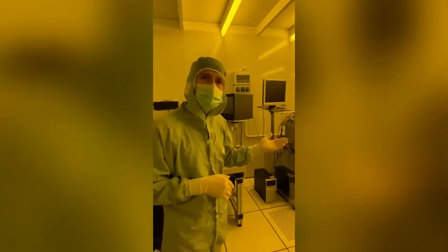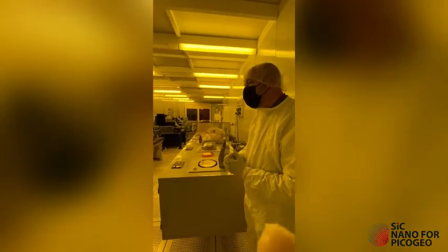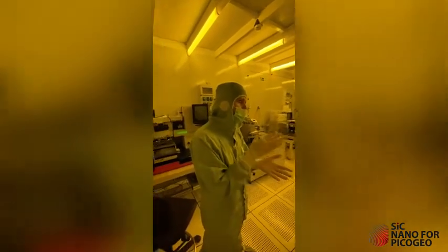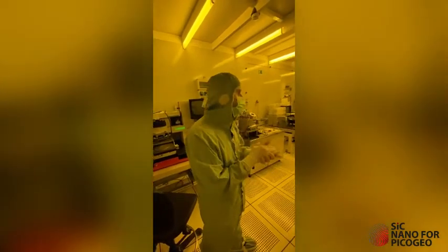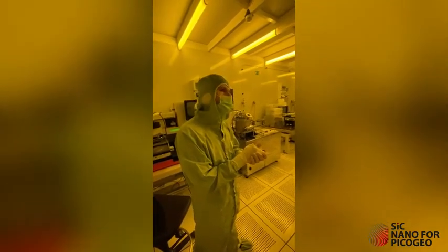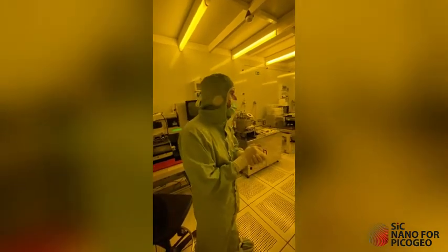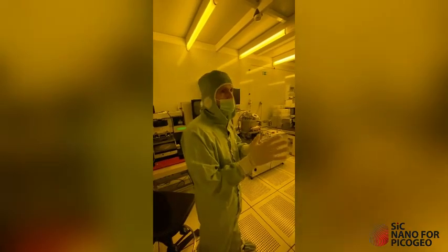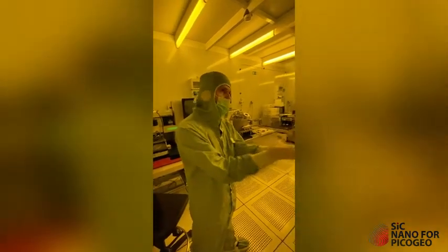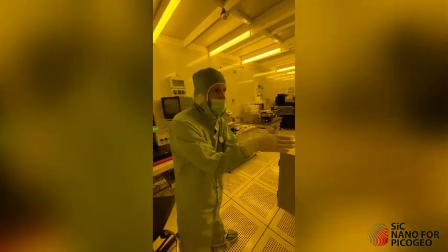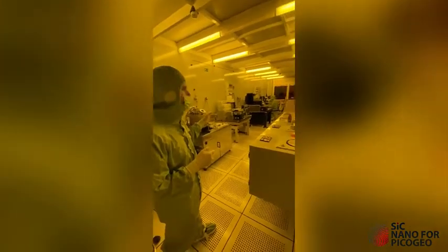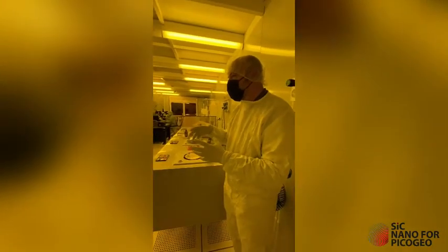We also have a bonding machine to bond wafers, for example to make microfluidic devices. What do you use to bond, glass or silicon oxide? It depends on the process. We have fusion bonding, in which we can fuse silicon with glass. We also have bonding with SU8, which is a photoresist, so it's a glue bonding. Also silicon and silicon dioxide on both sides, the fusion bonding. Fusion bonding uses higher temperature and pressure, and glue bonding uses a lower temperature.